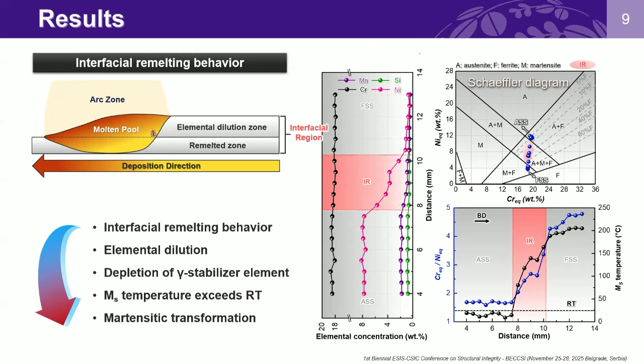To estimate the stability of the gamma austenite at room temperature, the martensite start temperature was calculated. It is obvious that the martensite start temperature exceeds room temperature across the interfacial region, indicating gamma austenite is unstable at room temperature. The equivalent chromium and nickel coordinates were also marked in the Schaeffler diagram.